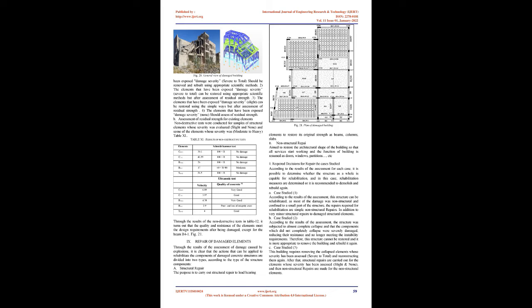B. Assessment of residual strength for existing elements. Non-destructive tests were conducted for samples of structural elements whose severity was evaluated as slight and none, and some of the elements whose severity was moderate to heavy, Table 11. Through the results of the non-destructive tests in Table 12, it turns out that the quality and resistance of the elements meet the design requirements after being damaged, except for the beam B4-1. Fig 21.